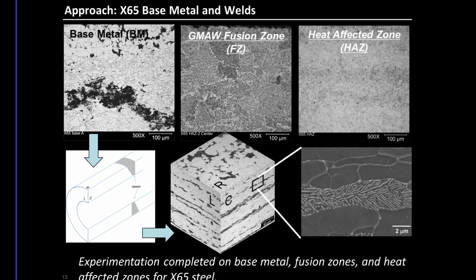So first, looking at the X65, if you look at the middle of the screen here at the three different orientations of the pipe, I have called them out as L, C, and R. Because this was supplied to us as a pipe, the L stands for the longitudinal direction, C for circumferential, and R for radial. And you can see this actually was a banded microstructure to begin with. What I mean by that is if you look in the L and C planes, you see these distinct regions of the darker phase, which is the pearlitic region, and then the lighter phase is the ferrite. And so this is just an artifact of the processing technique. During original solidification, you end up with this banded microstructure. But the microstructure overall for the base metal was a ferrite pearlite microstructure.